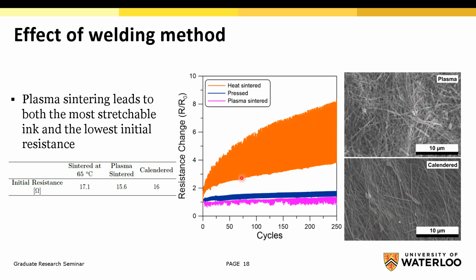And here you can see the heat sintered in comparison with pressed and plasma sintered. You can see the plasma sintered one has the lowest initial resistance and also the highest stretchability, which the magenta curve shows, the plasma sintered here.